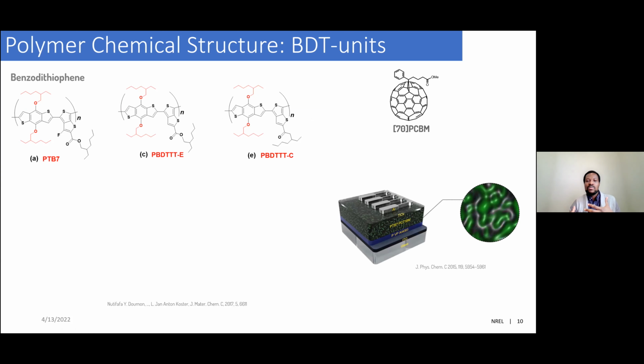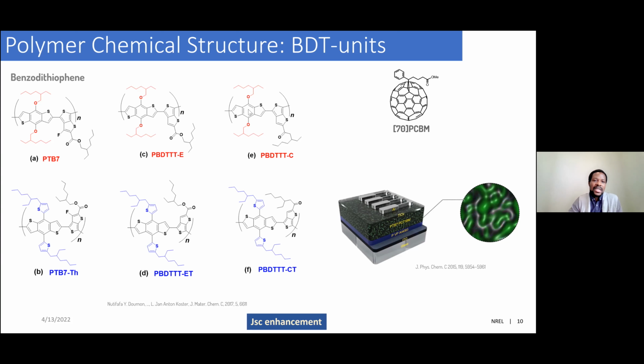Now, how do we move forward? Because the challenge is to increase this efficiency over time. So the chemists have been very supportive of the community, and they came with new ideas. What they did was to replace this side chain, especially the oxygen in the side chain, with a thiophene. And this gives a rather two-dimensional orientation of these materials in the thin film, which helps in transport and therefore enhances the current density.